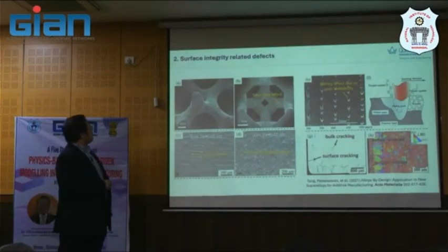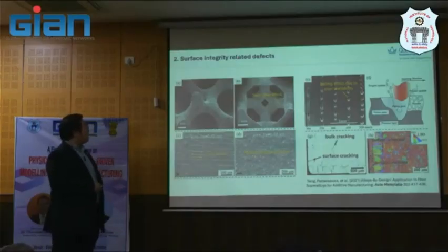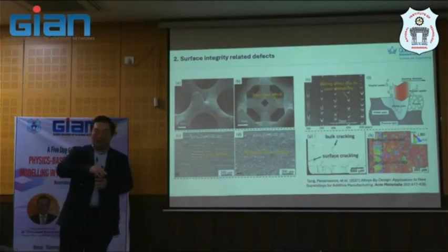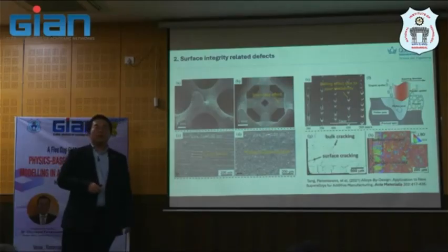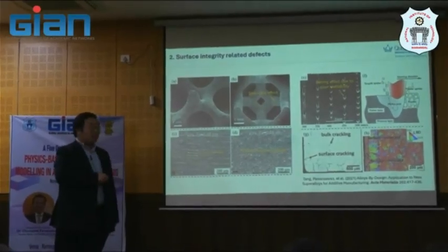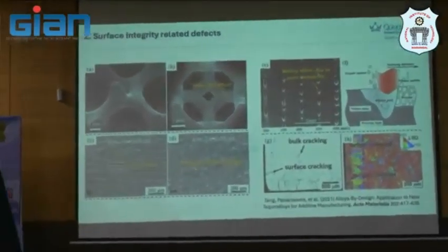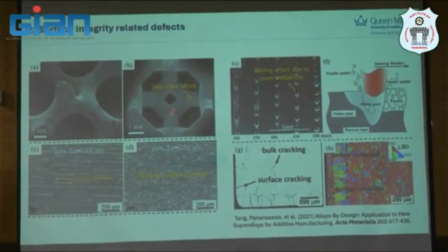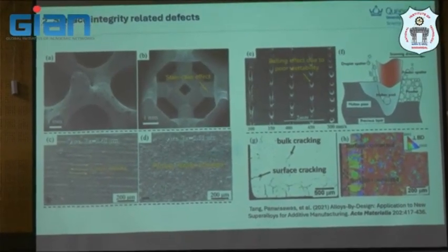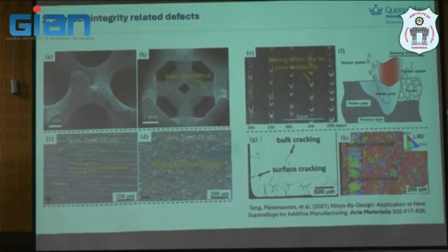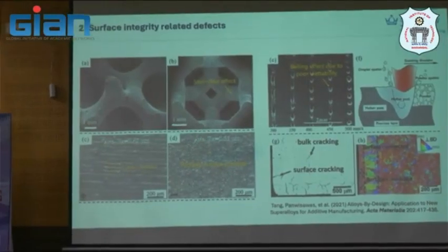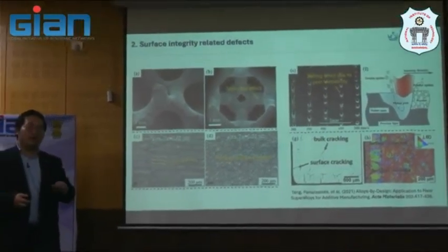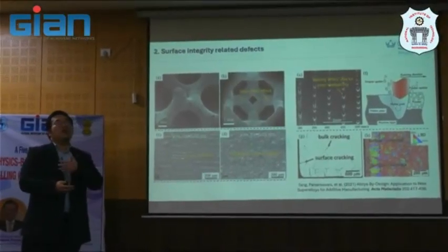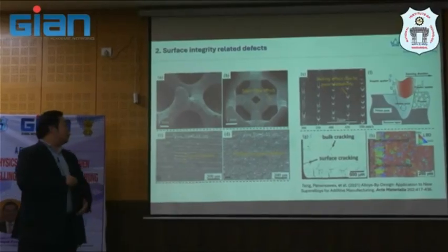Secondly, is about surface or integrity defects here. I mean, this is a staircase effect when you print something, related to layer thickness, as mentioned before. This may make your surface not very smooth, so it's about stepwise, something like that. That probably poses some challenge in the property when we later use this part. Surface roughness is another problem. Again, this is happening during melting, during printing. Actually, the surface roughness here, as you may know, may come from the quality of the powder as well as the way you print it, in terms of the optimized process conditions that you choose, laser scan speed, and the power that you use for this process.